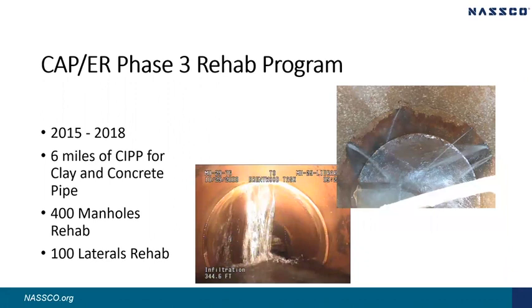So to continue on throughout our years of rehab here, 15 and 18 was another phase. Again, we did about 6 miles. We kept with our same process of going into an area and doing everything from the main lines, laterals, and manholes. And again, at this phase, we did about 400 manhole rehabs. And again, just to note, our manhole rehab process was we use a cementitious coating followed by an epoxy top coat.